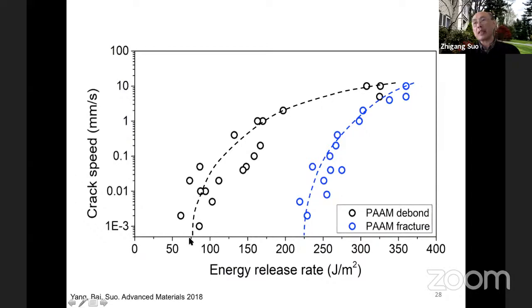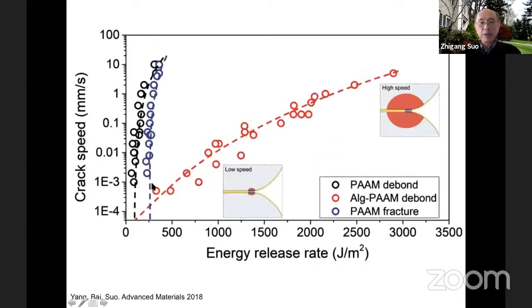So we take this as evidence that we're breaking alginate rather than breaking polyacrylamide. Of course, on the interface, the breaking causes a cohesive failure through the alginate rather than happening along the interface or inside the polyacrylamide. So we can ascertain and answer this question both visually, by looking at the fracture surface, and also by data. Another piece of data is very interesting.